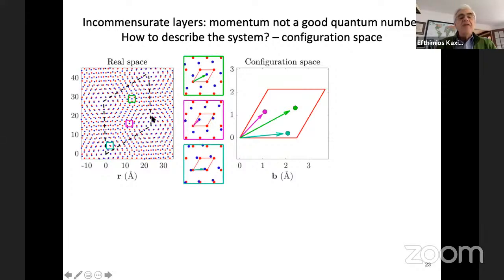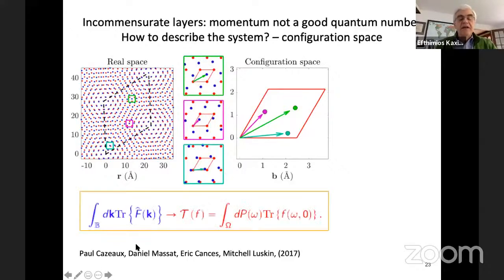So basically, you have these arrangements in real space. So these are the moiré patterns of the red and the green layer. But you can see that locally, you have different types of arrangements. So I'm blowing up these different regions. And you see the relative arrangement of atoms in this region or this region or this region. So you realize that what only matters is the different relative local arrangements. And you can translate everything that we did in K space, so these are the integrals that we typically do in K space, to integrals over local configurational space when you take into account all these possible local configurations between the two different layers.